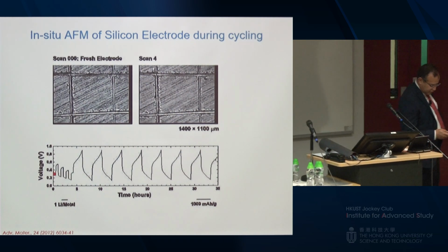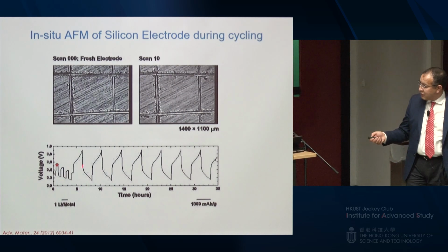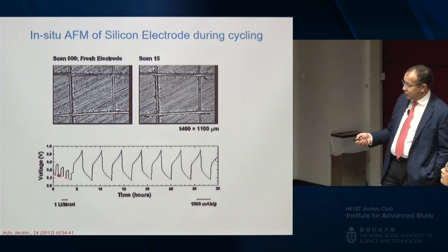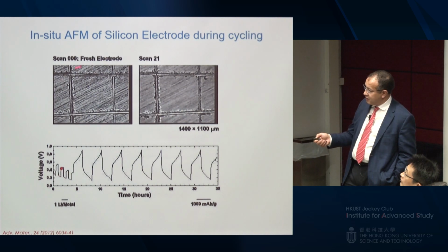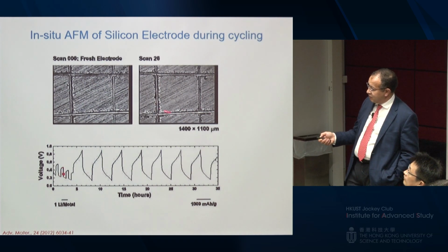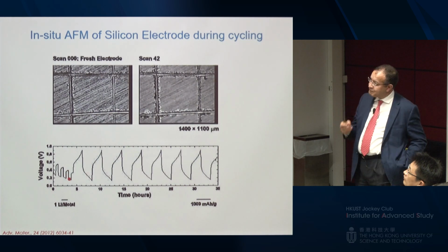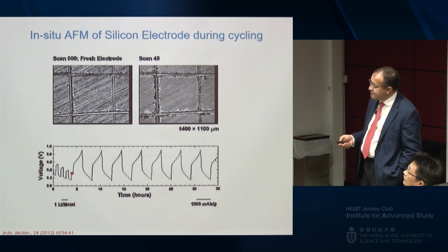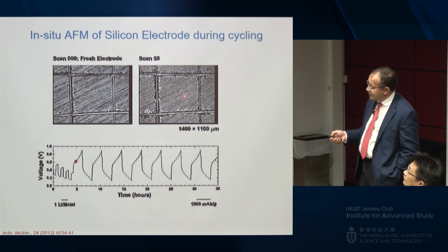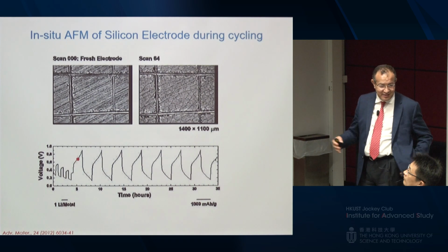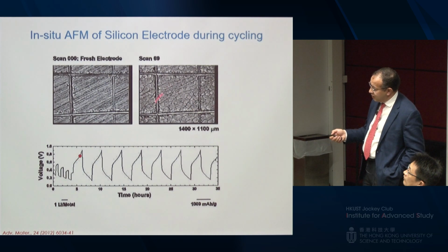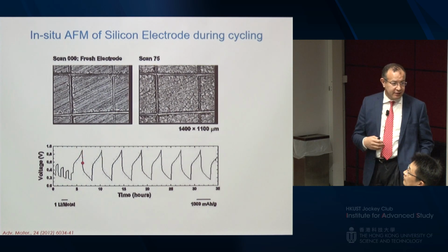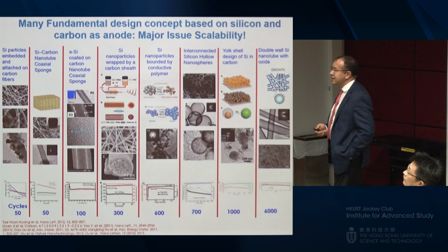Okay, so if you check out that red point here, at the moment we are not alloying because we are not really cycling, but this is the reference and this is the scan one that we are observing. So once this one starts alloying, when it starts coming here, you will observe what happened. This is in first cycle. So you can see now when it starts alloying, you can see the cracking start happening because of the expansion. And you can see it right there. And it will go back, and with time, it will start isolating. So that's an issue that needs to be addressed.